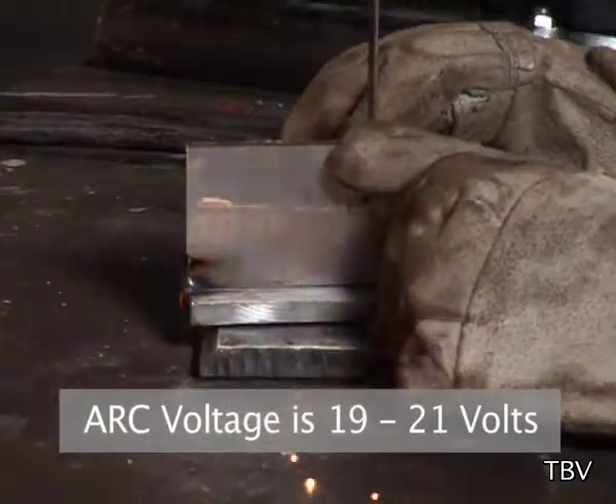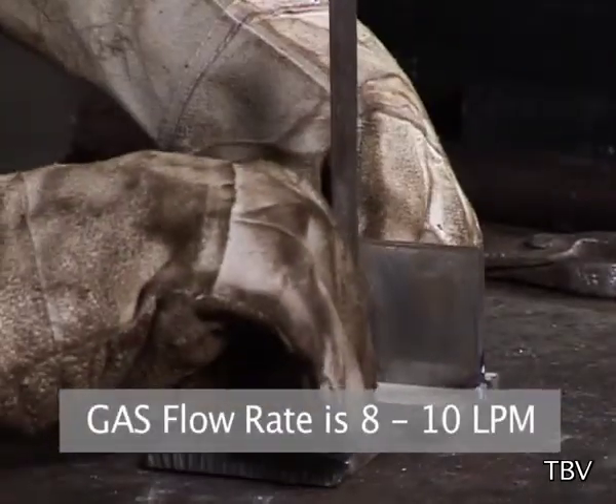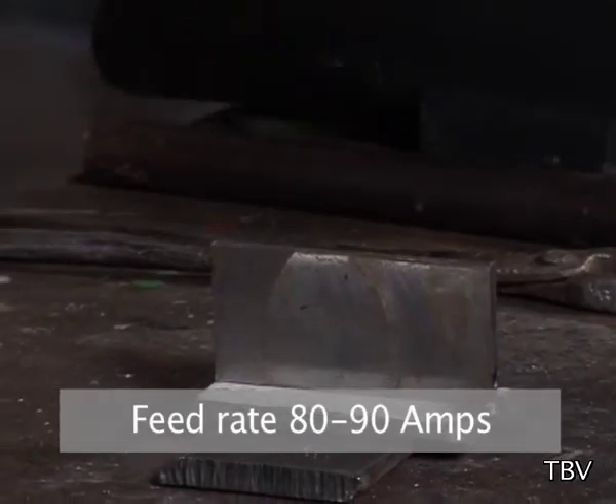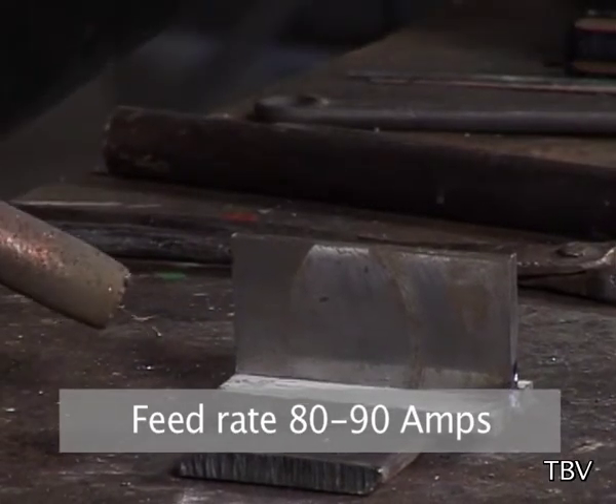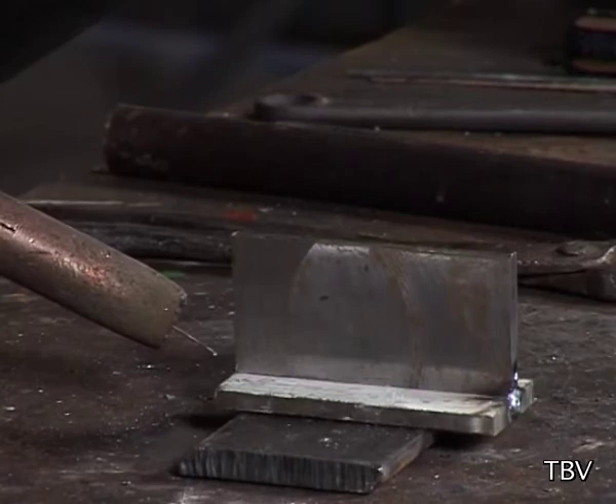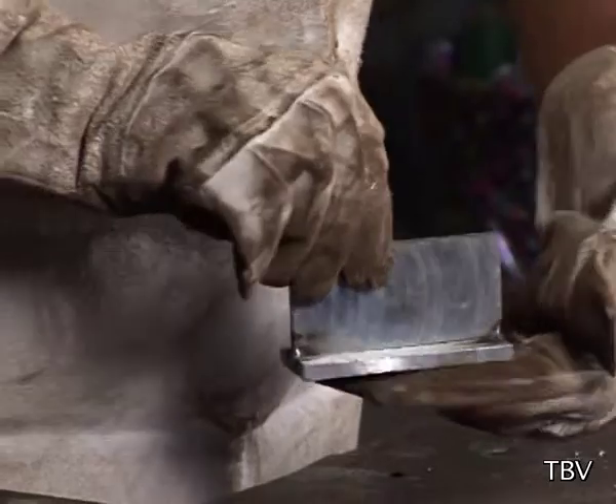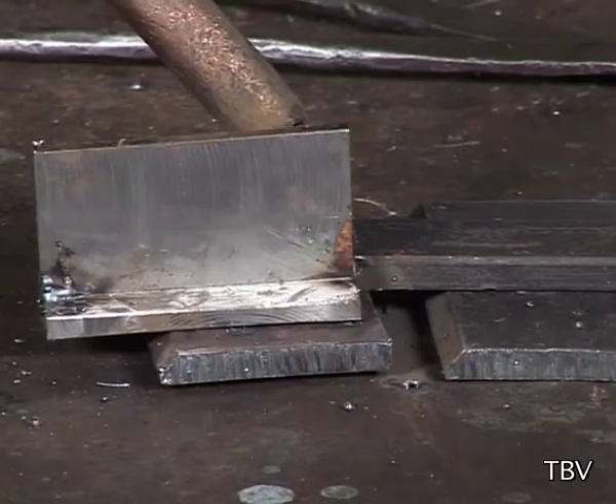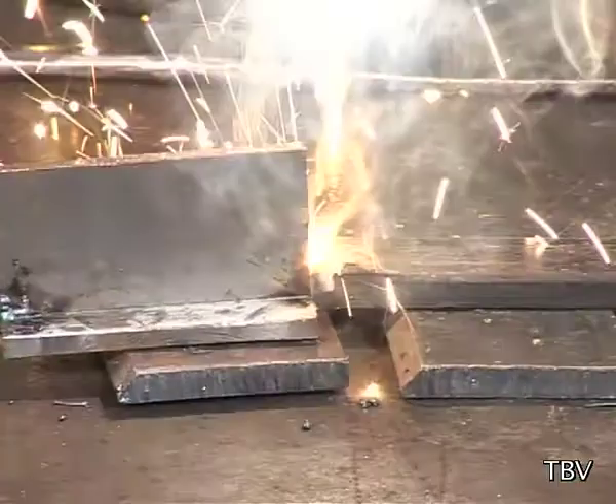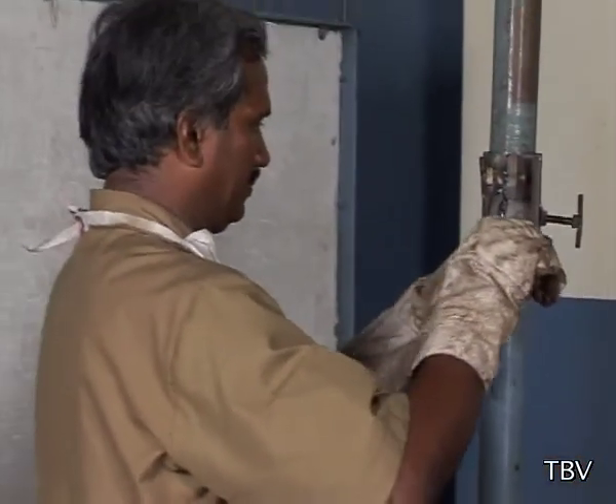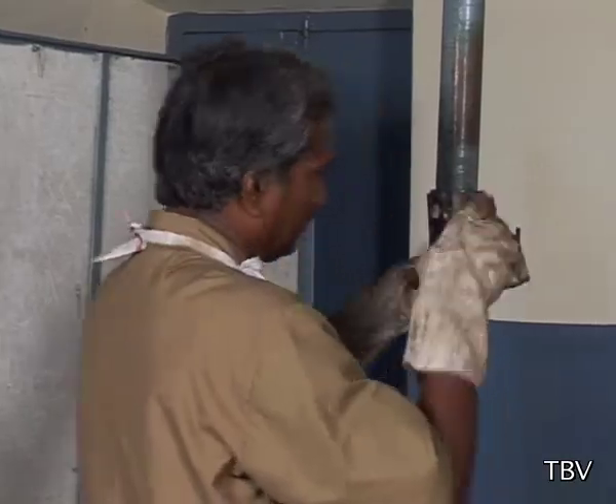Arc voltage is set at 19 to 21 volts. Gas flow rate at 8 to 10 LPM. Feed rate 80 to 90 amps. Tack a metal piece. Mount the job such that the plate is vertical and the scribed lines are in horizontal position using the job positioner. Hold the torch at an angle of 10 to 15 degrees to the job.